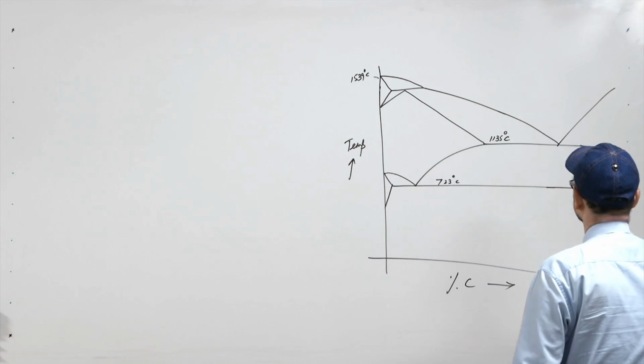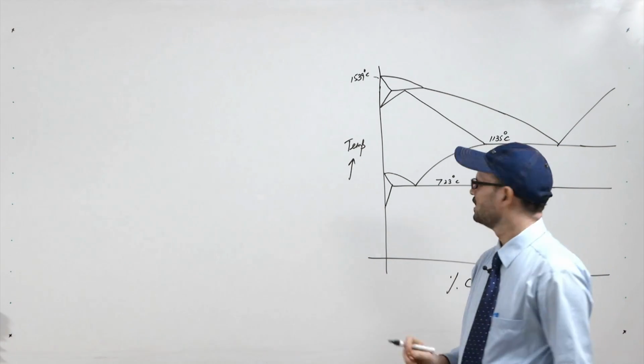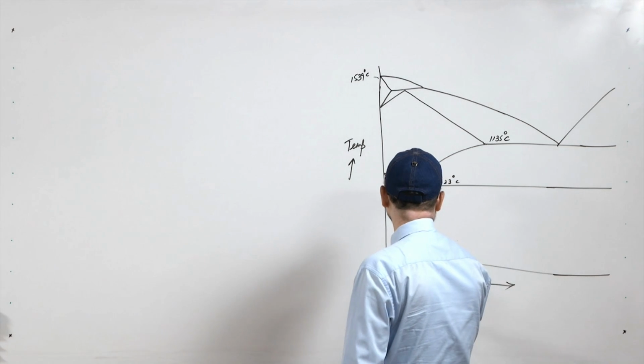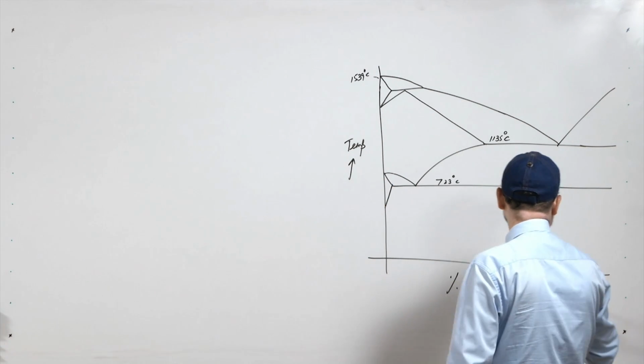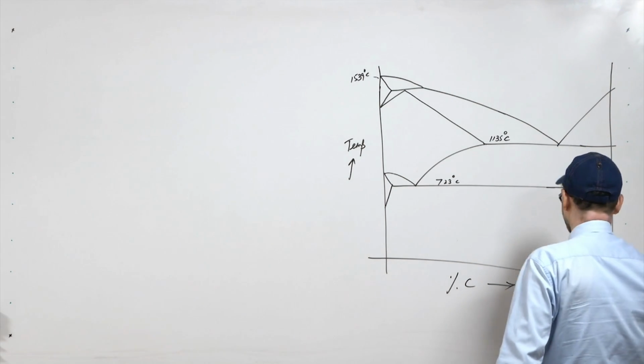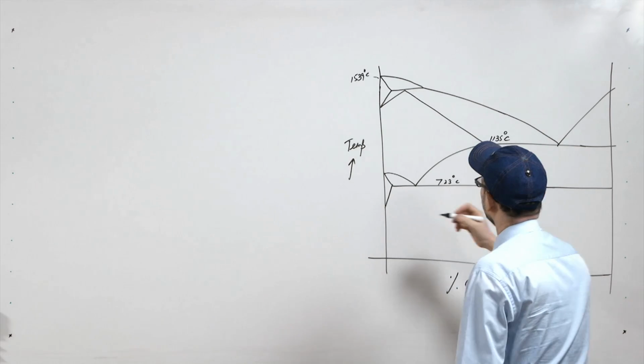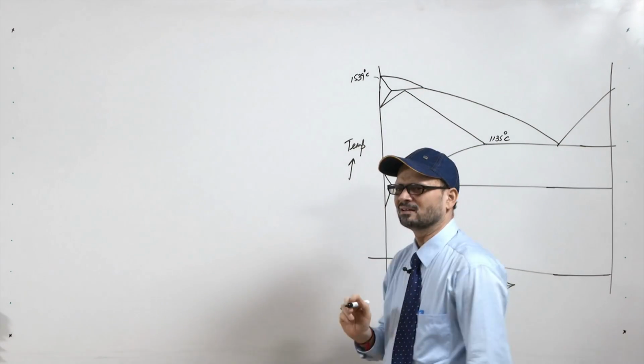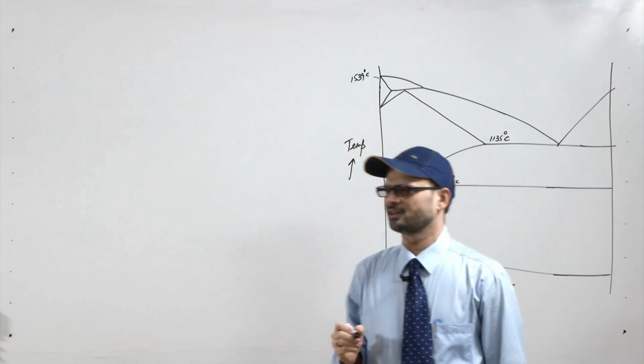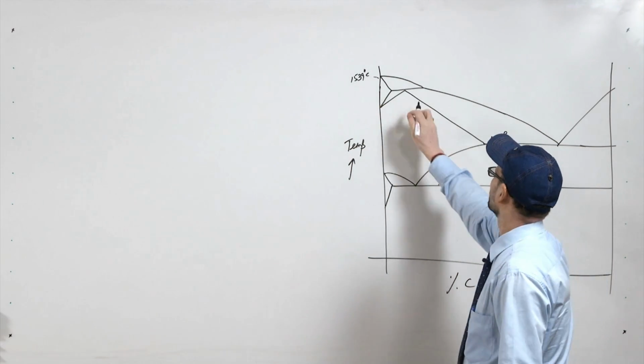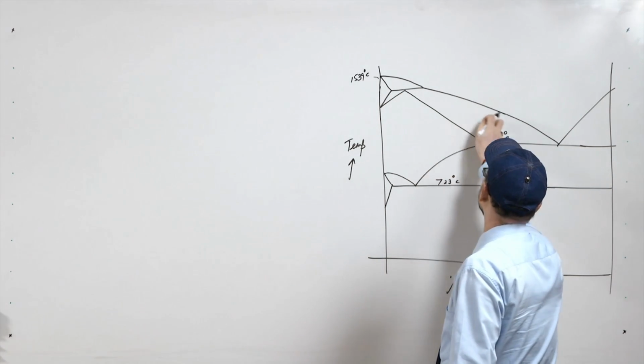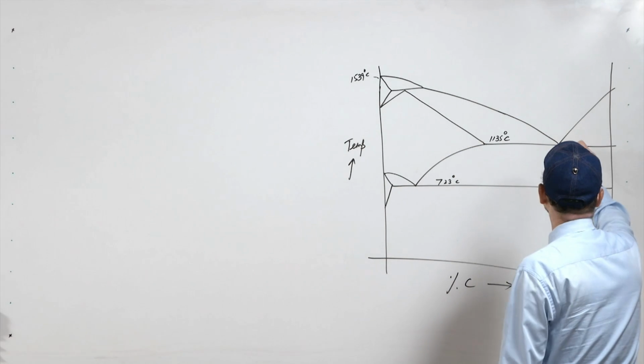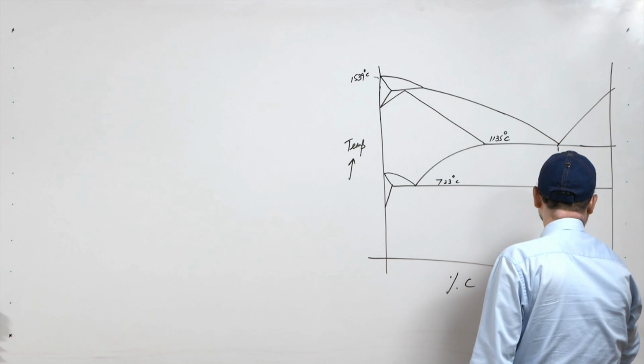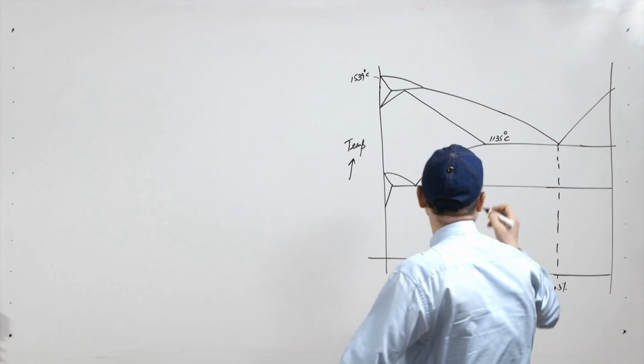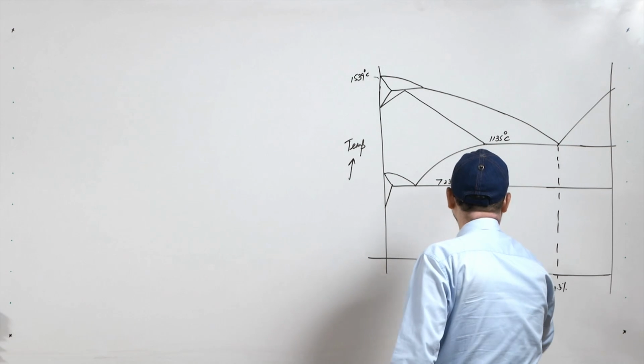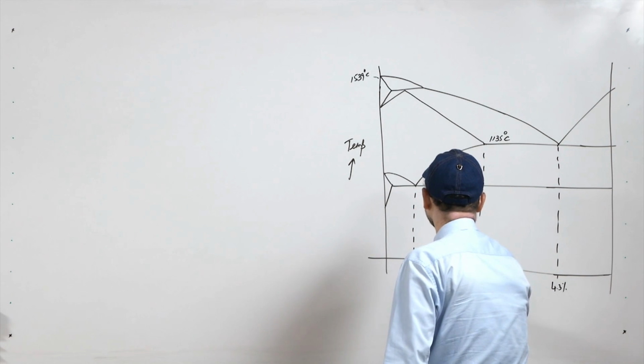As the carbon percentage is increased, this is 100% iron, and in this direction the percentage of carbon increases. When there is pure iron, it melts at about 1539 degree centigrade, but as the carbon percentage increases, this liquidus line decreases. This point is known as the eutectic point, where the carbon percentage is 4.3%, this is 2%, and this is the eutectoid point, 0.8%.